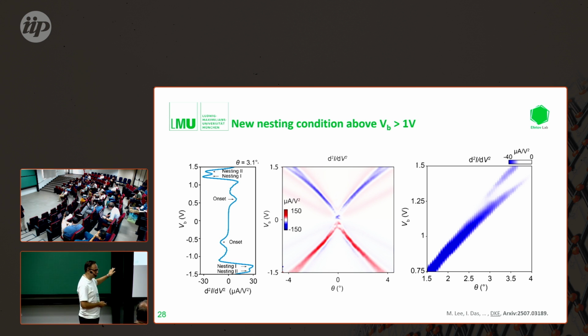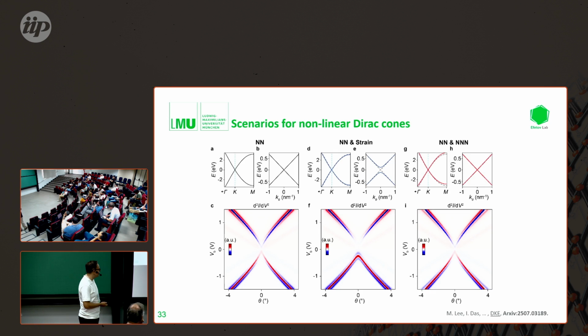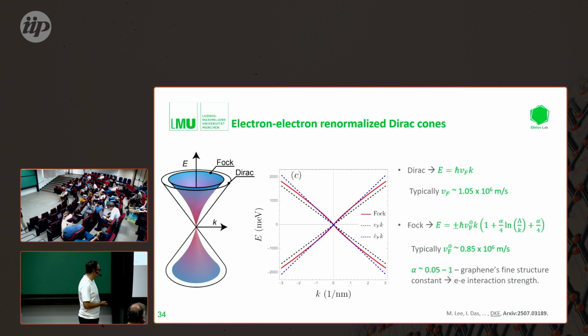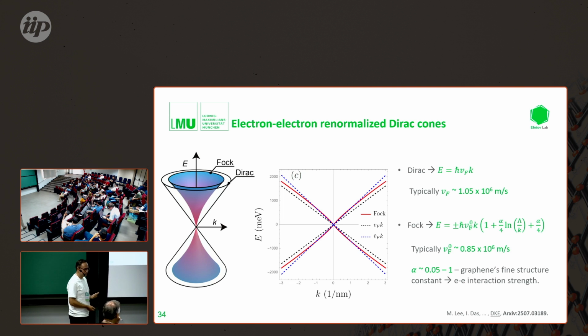So exactly. This measurement was done at room temperature, just because we didn't have the low temperature setup yet. So it's the first thing you do experimentally. What our theory collaborators did, however, is they tried to introduce a temperature-dependent effect. As far as I understand, the temperature-dependent effect can enter two ways. First of all, you introduce some temperature k_BT on your Fermi surface. And then the other thing is, one has to look at whether some of these alpha or lambda are temperature-dependent. But this is Coulomb, right?